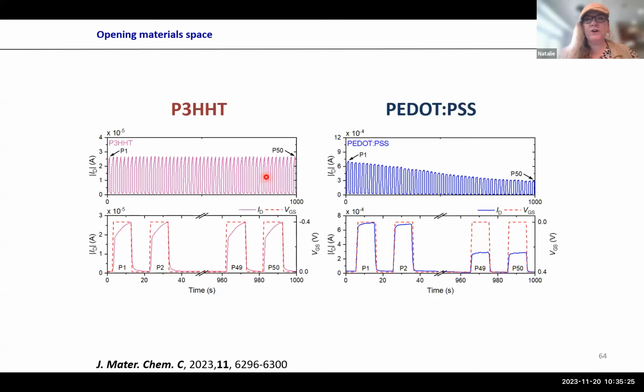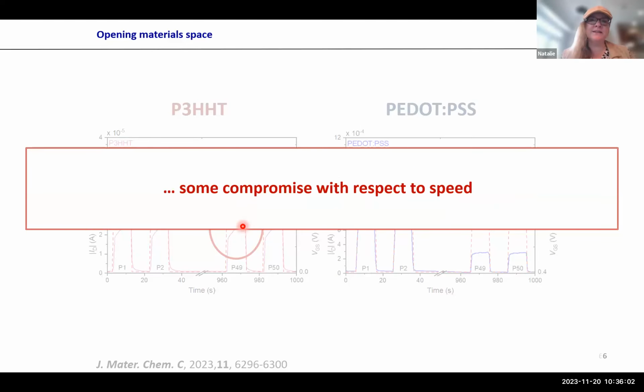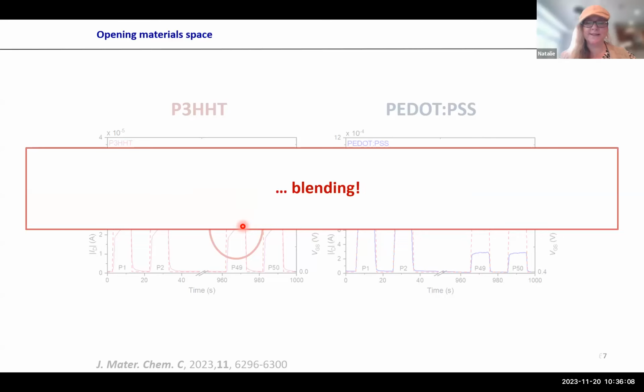When you look closely on the two systems, especially at early cycles, well, even later cycles, I should have put the circle actually here. One big problem of P3HHT is it's still drastically slower than PEDOT:PSS. So here you see you apply a gate bias, you can actually get the ions in, and you have a very rapid response. So the P3HHT, because of course it's less polar, is slower, and that can be a problem for certain devices. So we have stability, but we compromise actually with the response time of the, in this case, OECT.